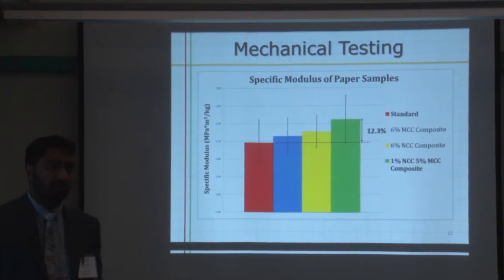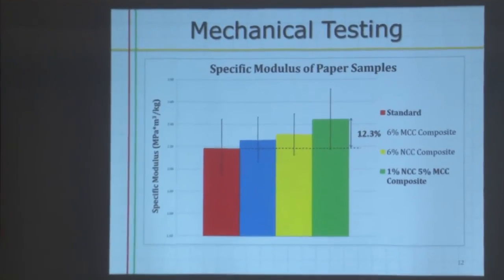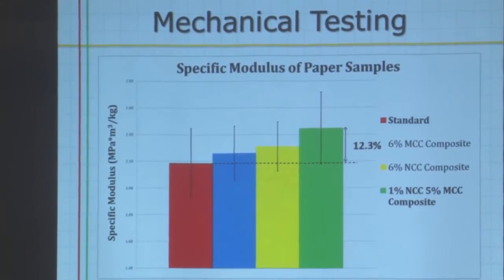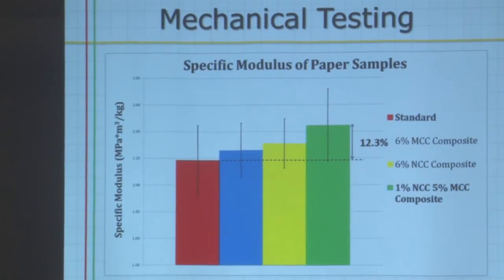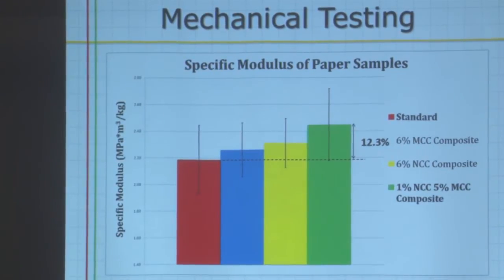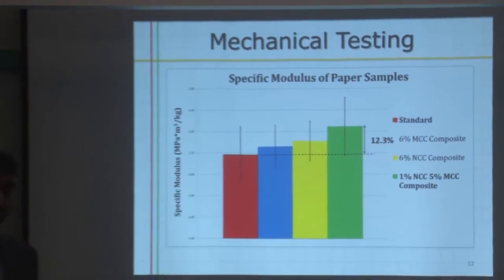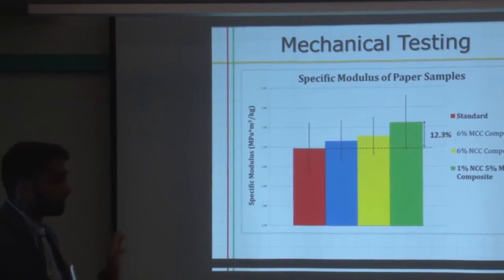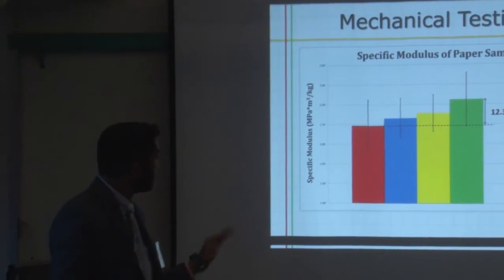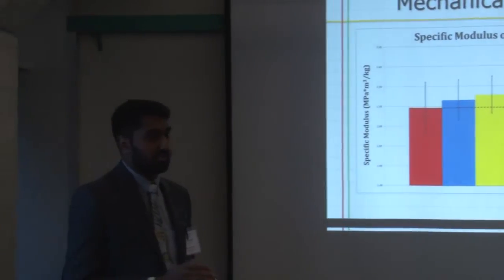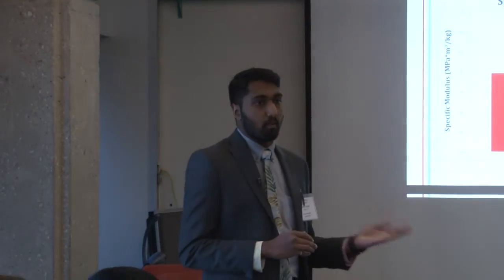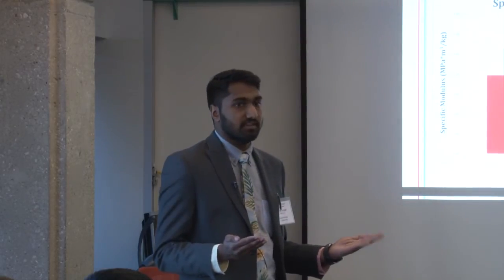We created 32 handsheets of varying compositions, and from them we made 88 test strips for tensile testing. From tensile testing, we were able to get the Young's modulus of elasticity, which, when normalized for density, will give you the specific modulus. Here you can see that there are 4 different compositions we looked at for this study. The red bar is our standard pure cellulose paper. The green bar is our 1% NCC, 5% MCC composite that we've been discussing. In addition, we also looked at 6% only MCC and 6% only NCC to make sure no funny business was happening where one fiber was doing all of the work.